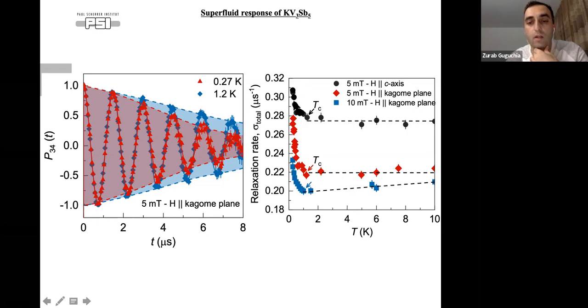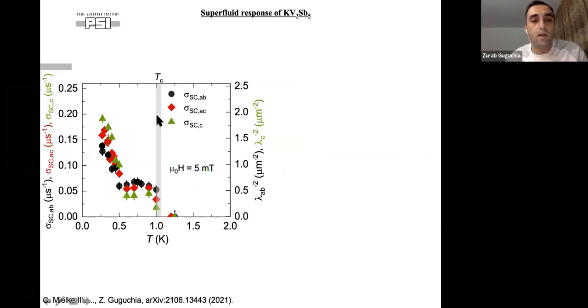So overall, the increase of the superfluid density at low temperature below TC is small. But you see this interesting two-step behavior within the superconducting state, and you have more or less linear temperature dependence. Recently, for the last few days, we have been taking data in the dilution fridge, so we can see that this does not really saturate. This could point to some kind of nodal structure, but at the moment we cannot make a sharp statement. At least it does not saturate as you would expect for s-wave superconductors.